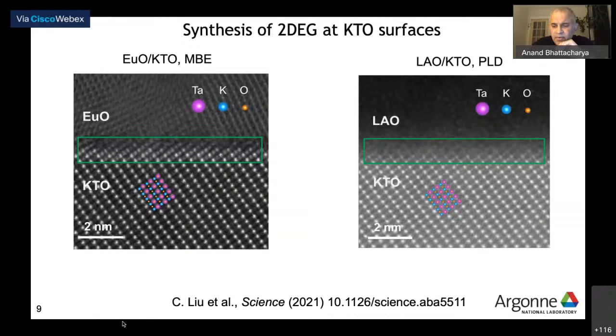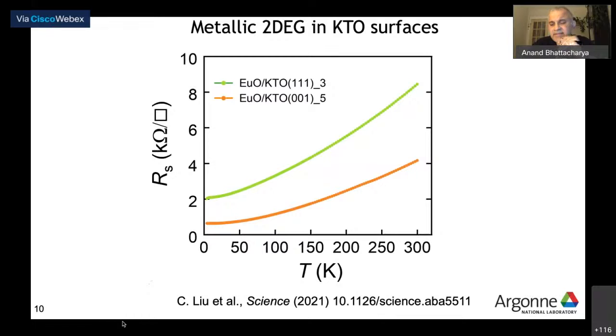All right. So consistently, what we found is that the 001 2-degs always have higher mobility for comparable densities than the 111 2-deg. All right. So that was the first finding, and we were actually very curious to see how these different things behave.